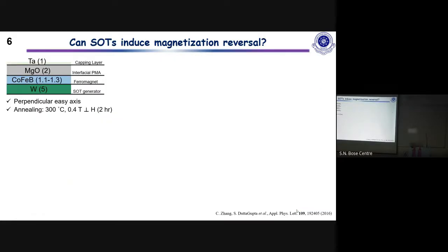So the first question that we actually asked way back in 2016 is, can the spin-orbit torques induce a reversal of an adjacent ferromagnetic sample? This is the stack structure that we used for our experiments. It consists of a tungsten layer, and then a ferromagnetic cobalt iron boron, and then an MgO and a tantalum cap. This was grown by sputtering and then subsequently annealed. After this annealing, we get perpendicular magnetization of the cobalt iron boron. All the grown systems which were not annealed, in our case, have an in-plane magnetization.